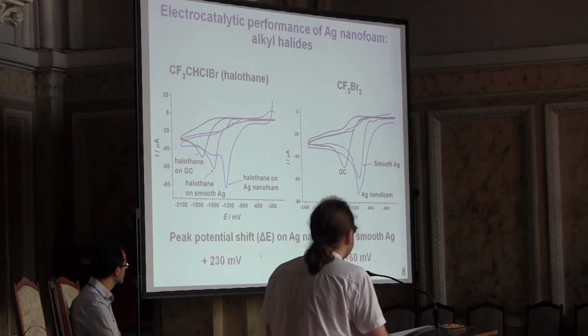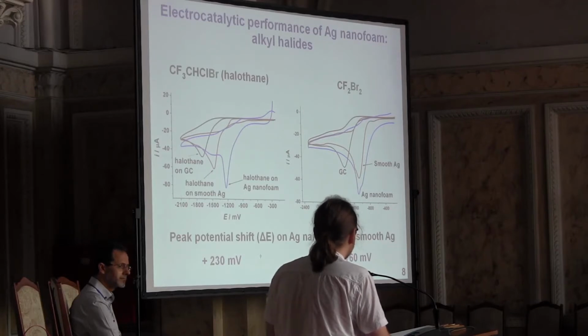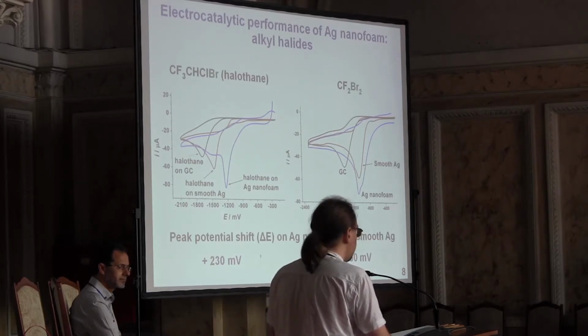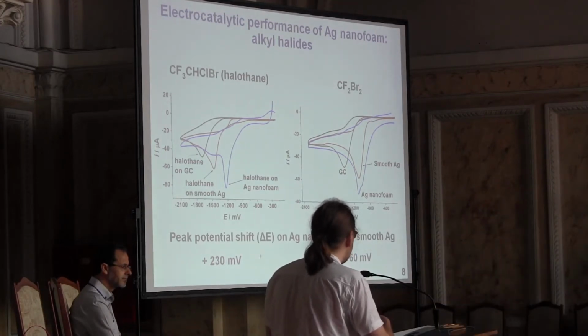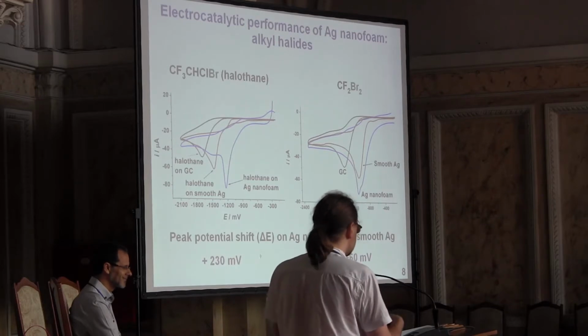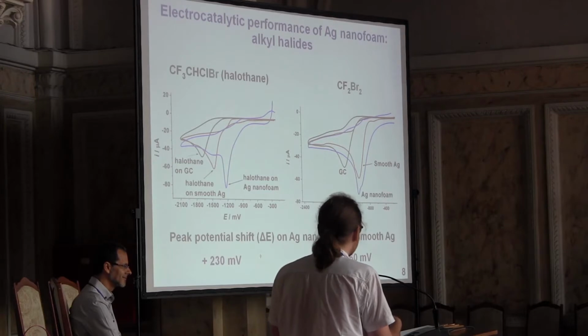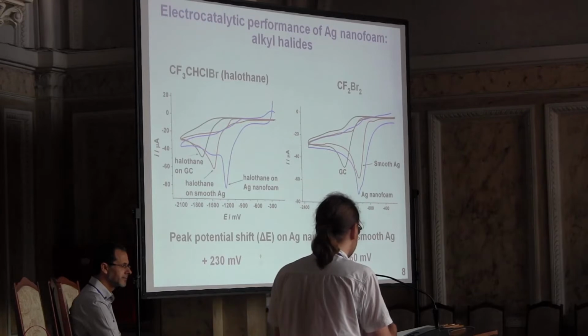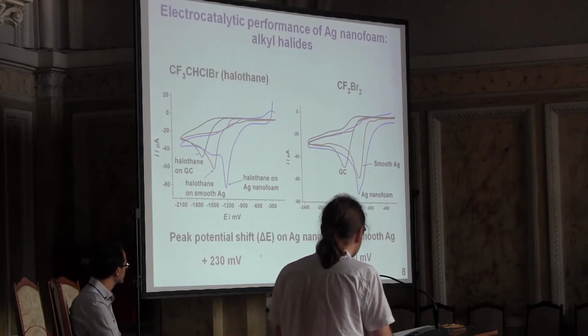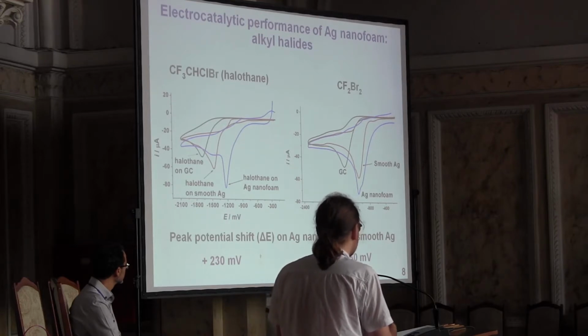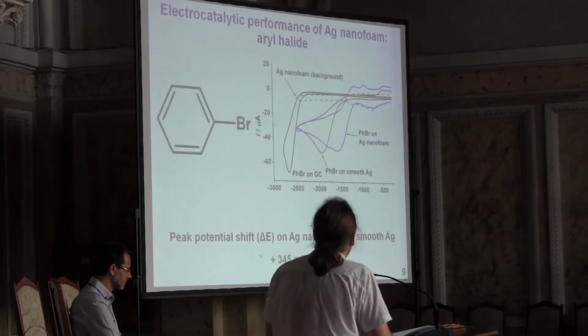We can explain such difference by a slower diffusion of halothane or by faster reduction. So in the case of halothane, it could be suggested that only the most active sites can participate in such a reaction. And in the case of dibromodifluoromethane, less active sites also take part.